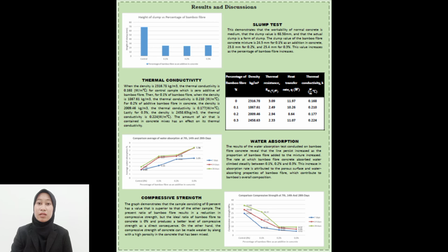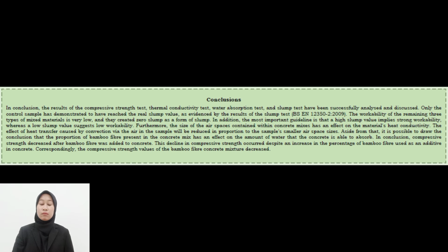Aside from that, the reduction in strength is typically caused by a lack of adhesion between the bamboo fiber and the concrete mix. In conclusion, the results of the compressive strength test, thermal conductivity test, water absorption test, and slump test have been successfully analysed and discussed. Only the control sample has been shown to reach the real slump value, as evident from the result of the slump test. The workability of the remaining 3 types of mixed materials is very low and they create zero slump as a form of slump.